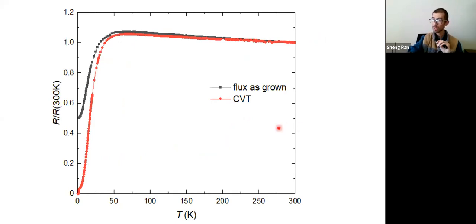We can grow these samples with two different methods. We can grow them with chemical vapor transport, or we can grow them with flux. Here, I'm showing the resistance as a function of temperature for the two different methods. If you grow with chemical vapor transport, you can see it really goes to 0. But if you grow it with flux, the RRR, the resistance at room temperature divided by the resistance at the lowest temperature, is only 2, indicating there are a lot of impurities or defects. In that case, it does not go to the superconducting state. This indicates the superconductivity is very sensitive to either impurities or defects, which likely means it is unconventional.